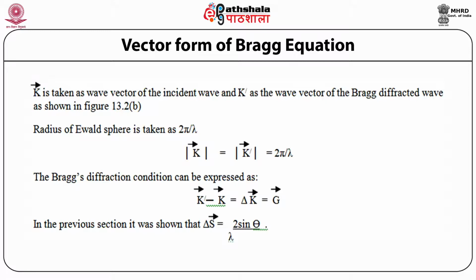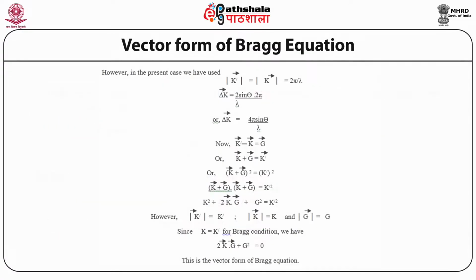In the previous section, it was shown that delta S vector is equal to twice sine theta by lambda. However, in the present case, we have used modulus of K prime vector equal to modulus of K vector is equal to 2 pi by lambda. Delta K vector is equal to twice sine theta by lambda into 2 pi, or delta K vector is equal to 4 pi sine theta by lambda.